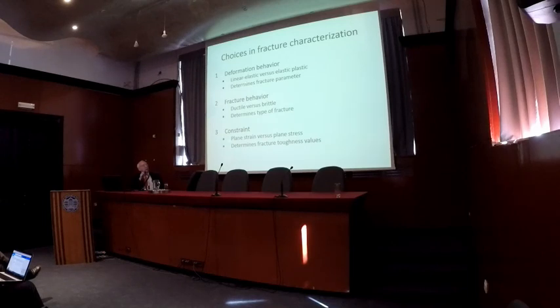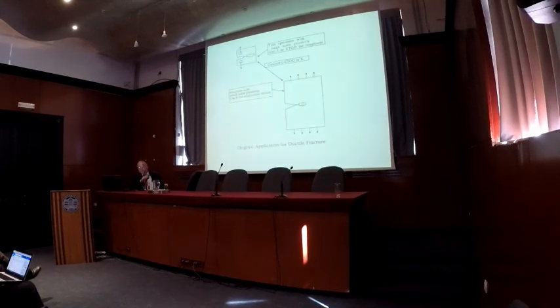People often confuse constraint with these two. I look at constraint as being thin specimen, plane stress, thicker specimen, plane strain, and plane strain usually has lower toughness than plane stress. One of the things that was done early on in developing nonlinear fracture parameters was to be able to use smaller specimens and not that 24-inch specimen I showed you. With the smaller specimens, we get a J or a CTOD critical fracture. And then if you have a big structure, you could use perhaps the K. And then there's a conversion from J or CTOD to K. And the conversion is essentially part of the equations that I showed you earlier. I won't show you that again. The advantage of doing the analysis in linear elastic behavior is the fact that you can superimpose loads. And it's much easier.